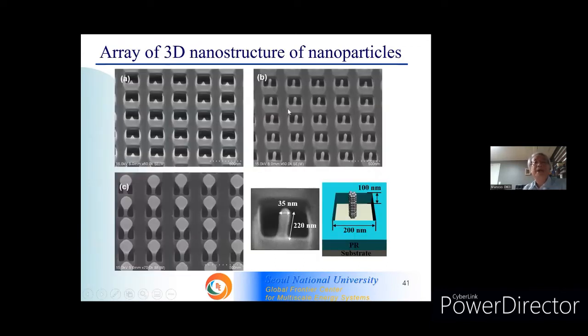Depending on the PR shape, you can make a real nanoscale column, diameter 35 nanometers, height 220 nanometers. Even this very, very small column consists of 1,000 small nanoparticles, a very compact structure.